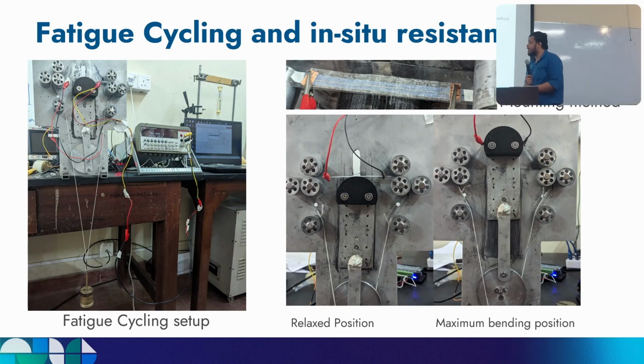After sintering, each and every sample was mounted on this fatigue cycling setup, which is the bending setup. So this is how it was mounted. The resistance was analyzed in real time while it was being bent. It starts from here and goes up to here. The interconnect is over here. It is bent using a 2-inch mandrel, so the radius of bending is 2 inches. This was done over time, and the real-time resistance change was recorded using a digital multimeter.